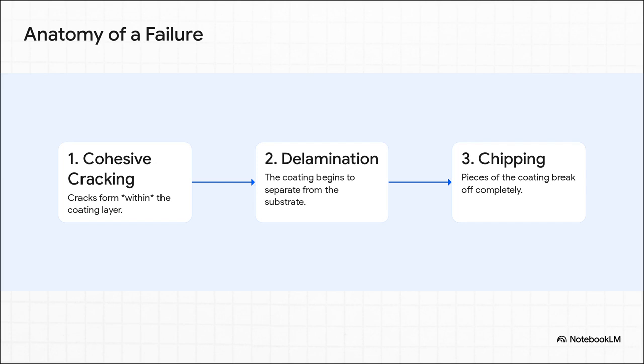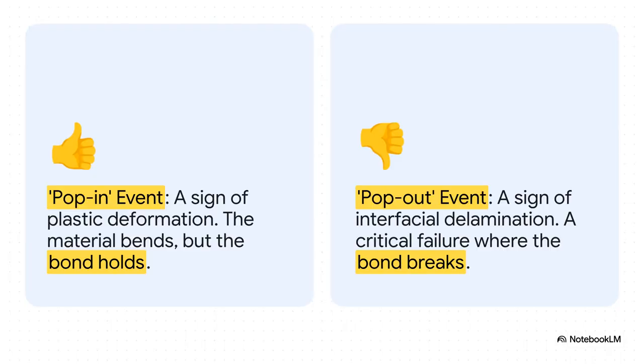It all starts with, number one, cohesive cracking. That's when these tiny fractures start appearing within the coating itself. Then the real trouble begins at number two. The coating starts to physically lift away from the surface. That's interfacial delamination. And finally, it all ends with number three, chipping or spallation, where chunks just break off completely. Game over.